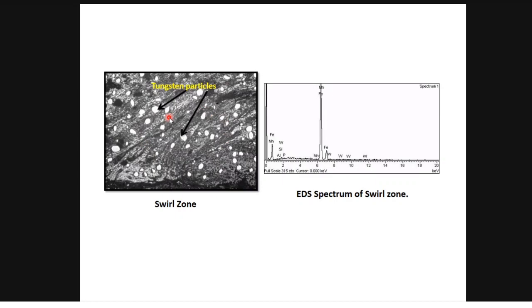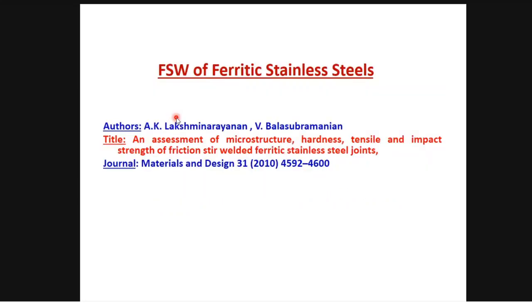That's the reason the hardness is high and toughness is lower, and strength is high and ductility is lower, because of the presence of this tungsten particle. The tungsten particles came from the tool material because of the wear that took place. So though we are making the joints, the tool wear is minimum, a very small amount of wear has occurred there.